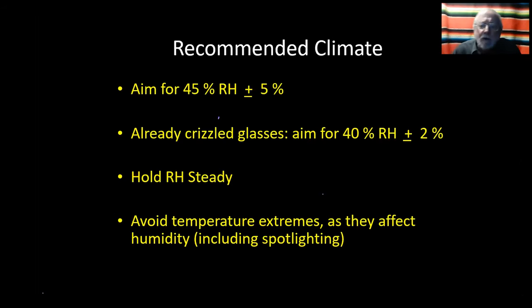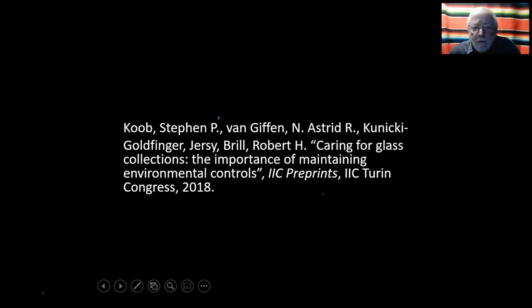We're not talking about crizzled glasses with archaeological glasses because, in a sense, it's easy to understand that archaeological glasses cannot crizzle. They've already lost their alkali from burial. So there's no more alkali to be leached out and cause the instability that happens with crizzling. But keep that RH steady. As we all say in conservation, a steady environment is much better than a fluctuating one. And avoid extremes, both in humidity and temperature. And again, this was published just recently in the IIC preprints of the Turin Conference in 2018.